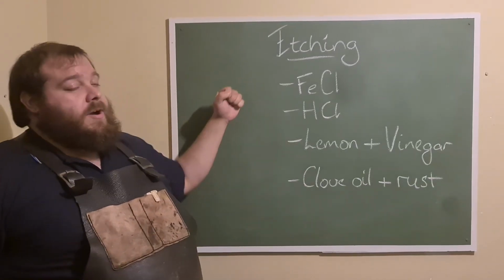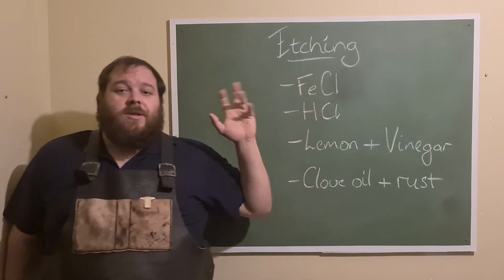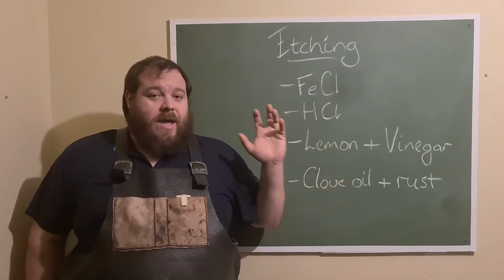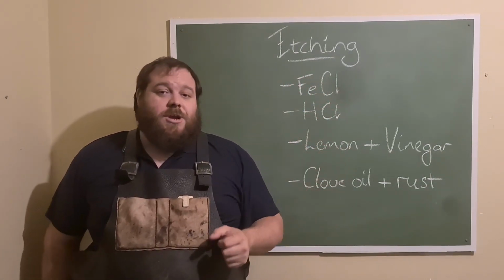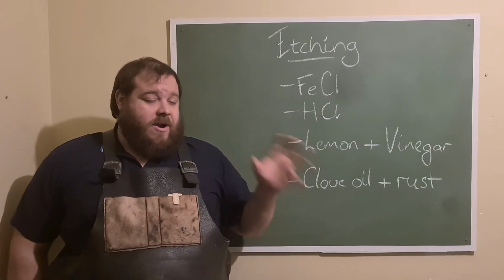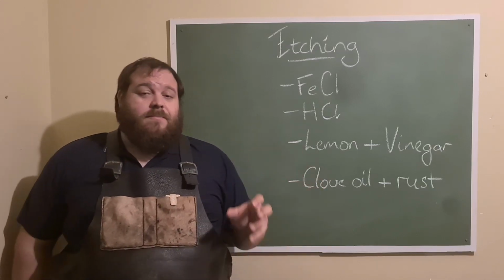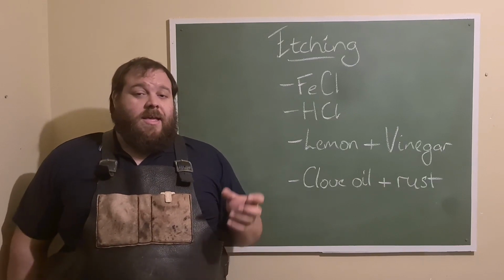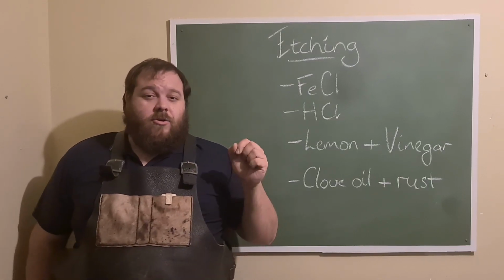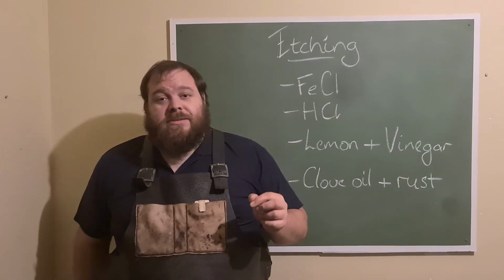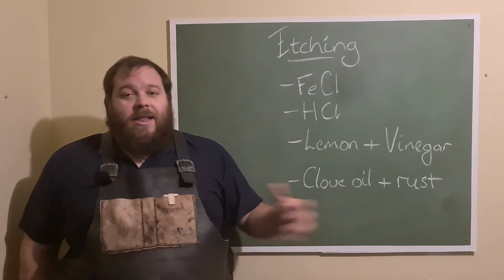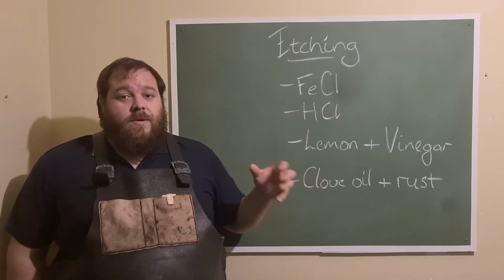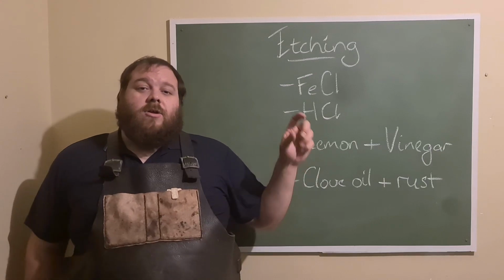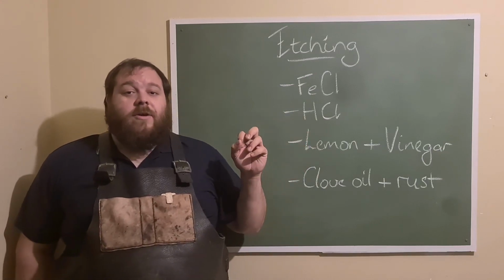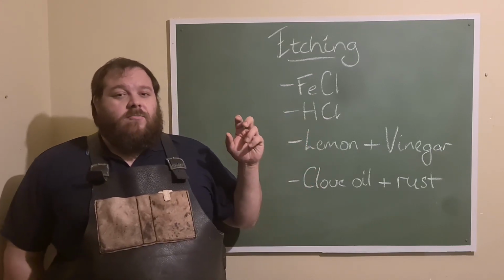Starting from the top is ferric chloride. It is the standard for all knife makers around the world to etch Damascus with and etch Hamon. It is very effective, it is very fast, but it is also very aggressive. It will show every little grain in your steel, which means that if you have some form of alloy banding, if it's W2 or W1, then you'll probably get a lot of flecking in your Hamon. It won't be very clean looking, it'll be very rugged looking.